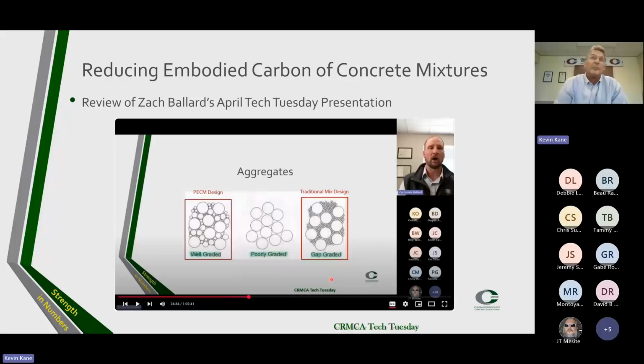But you can optimize and make more sustainable and reduce some of that paste content if you optimize your aggregate grading. Now, that's where you take more than 2 types of aggregate: a fine aggregate, a coarse aggregate, and an intermediate aggregate, and find that well-graded version of this. And if you can do this with your aggregates, you're going to use less paste, you're going to use less water, you're going to use less cement, and you're still going to have good results. So that's what's meant by optimizing your aggregate. There's a lot of benefits to optimizing your aggregate, sustainability being one of them, because as you optimize your aggregate, you're going to be able to reduce your cement content.